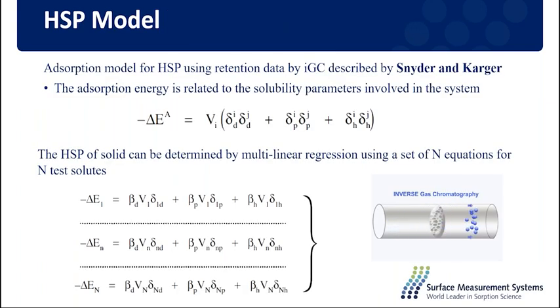And the last model, the last calculation, which is also implemented into our SCA software, is this model from Snyder and Karger, which is based on the adsorption energy of the different probes. This calculation also provides you the three components, the dispersive, the polar, and the hydrogen bond component of solubility parameter. But this type of application allows you to measure the solubility parameters below the glass transition temperature or above glass transition temperature. So any temperature range where you are interested in the solubility parameter.